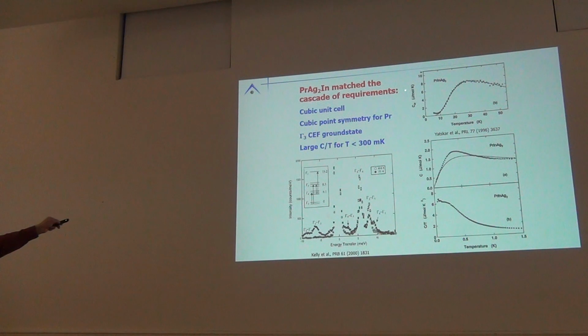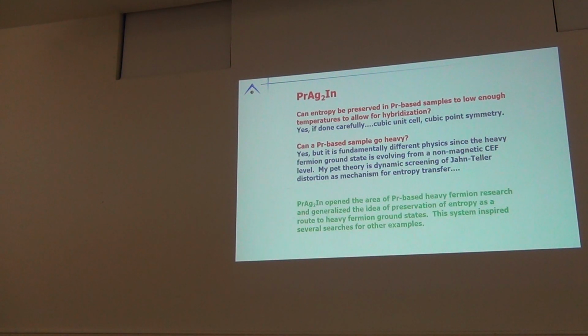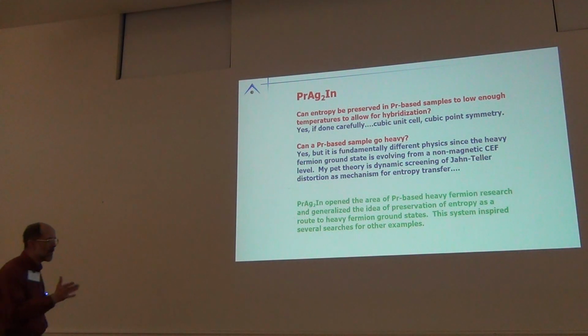We could measure specific heat. We could look at this in C or C over T at low temperatures. The high temperatures we could fit to the Schottky anomalies. The low temperature had a linear specific heat. If we plotted C over T versus T, it rises and saturates at 6 joules per mole K squared. That is a very heavy fermion if that's an electronic specific heat. So, can entropy be preserved to low enough temperatures for praseodymium to hybridize? Yes, but you have to be careful to preserve your entropy. Can praseo go heavy? Yes, but it's a different type of heavy fermion because this is a non-magnetic doublet.